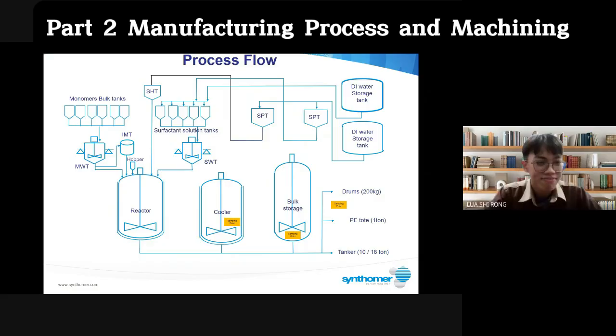The monomers will charge into here, MWT. MWT is the monomer weighing tank. At batch start, the monomer will transfer from the storage tank into the MWT, and partially from the monomer weighing tank, about 5% to 10%, it will transfer into the initial monomer tank. What the initial monomer is: during reactor start, the polymerization is an exothermic reaction, we call it. When the reactor wants to start polymerization, it needs some monomer to react with the initiator, with the catalyst.